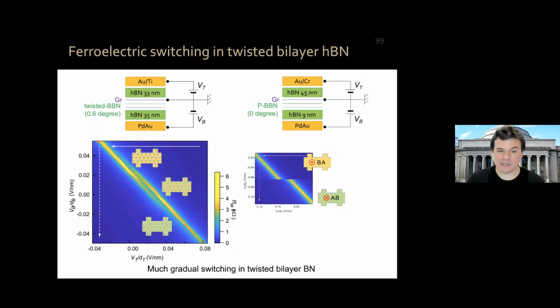And now you can see that the resistivity, initially one domain is dominant. This domain now slowly decreases while the contribution from the other domain grows as the electric field is changed, so that then becomes dominant, okay? So now we have a gradual transition between these two domains, the contribution to the resistivity of these two domains, rather than an abrupt switch as it happens for 0 degree angle, yeah?